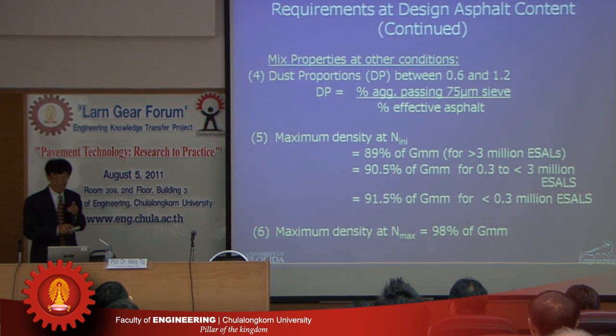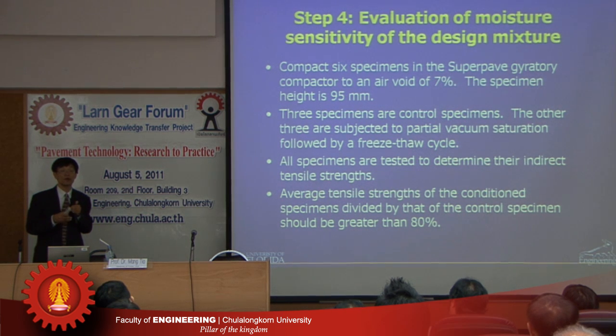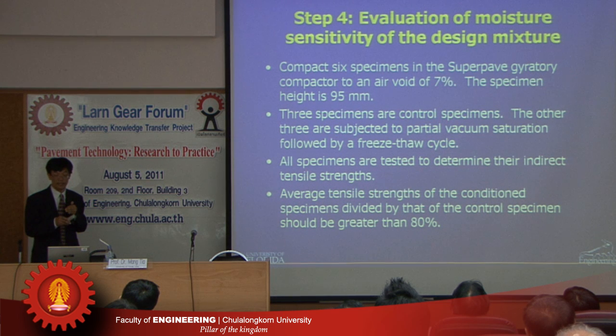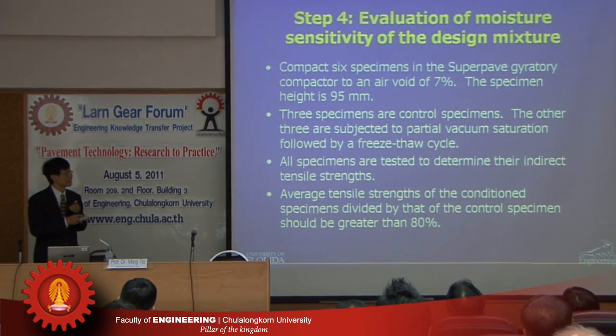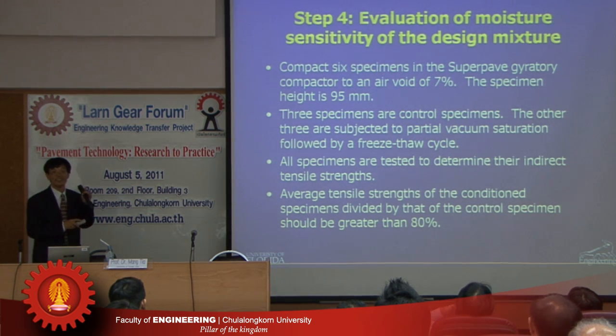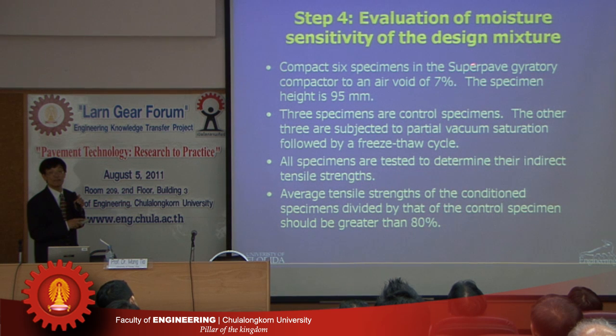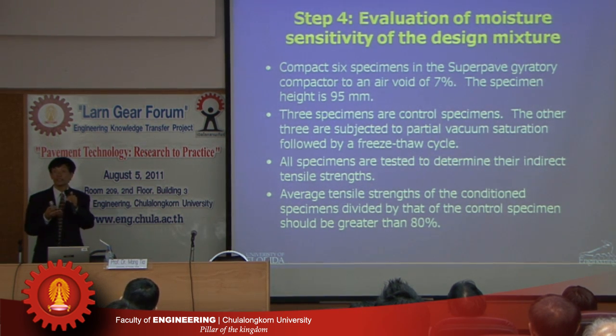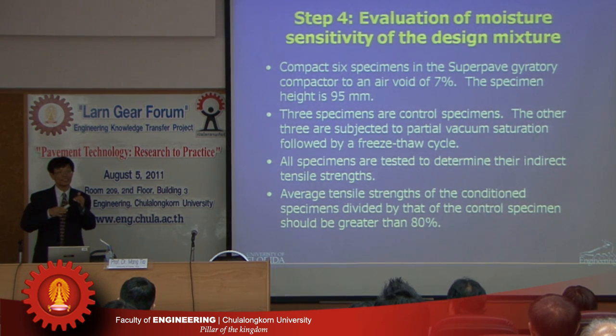There is also a requirement that the mixture not have problems with exposure to water. A water sensitivity test is conducted. The mixture with the designed composition is compacted to 7% air void — not 4% — because when you design at 4% air void, the mixture is actually initially constructed at about 7% air void. The 4% condition corresponds to the state three to five years after construction. So the water sensitivity test uses specimens compacted to 7% air void.